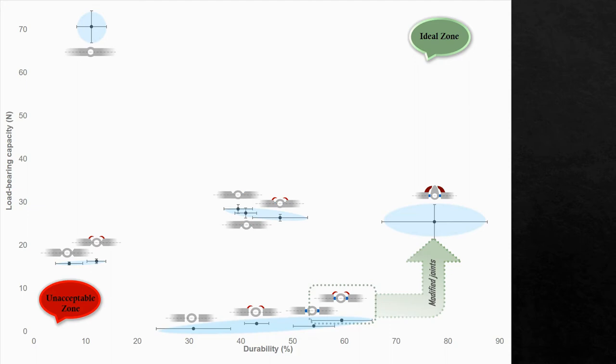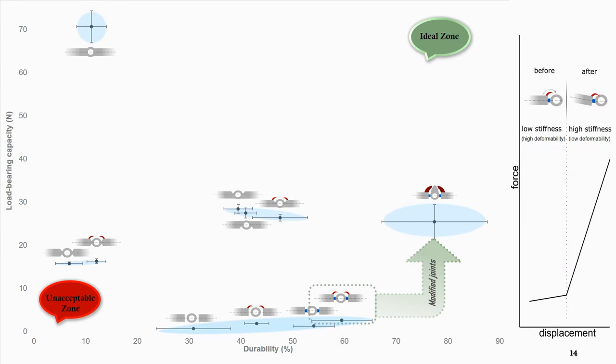In comparison to the fused joints, flexible joints showed poor load bearing capacity. However, this could be improved by several times using rigid spikes. This is how spikes activation works at the joints. Similar to the spikes on the insect wings, spikes in our 3D printed joints worked as mechanical stoppers and provided the joints with two deformability regimes.